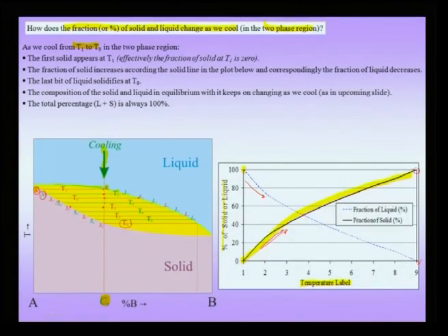Now, it has to become richer in B, because S2 is richer in B, and correspondingly, suppose you go to even lower temperature like S4, which is even richer in B. That implies that the solid which formed at a higher temperature like S2 or S3 has to change its composition, so that it becomes commensurate with what is dictated by the phase diagram. And I am assuming that at every temperature, though I am cooling, I am cooling slowly enough that equilibrium is maintained. Therefore, at S4 the composition of the solid is different from that of the liquid, and this implies that because it is a solid state, there has to be some diffusion taking place, so that the composition is made uniform corresponding to that temperature label, for instance S4.